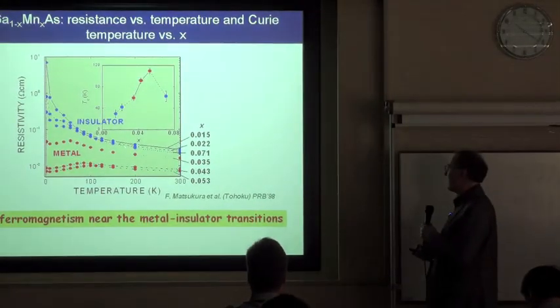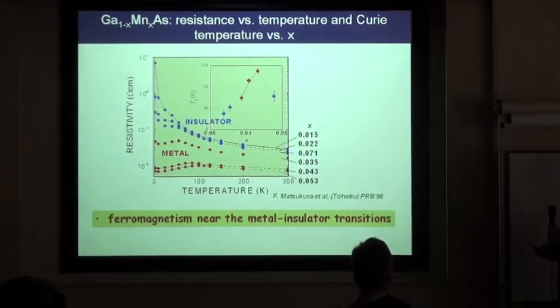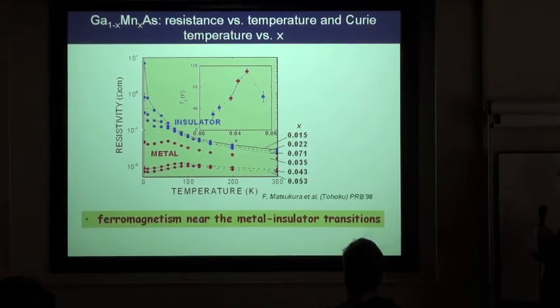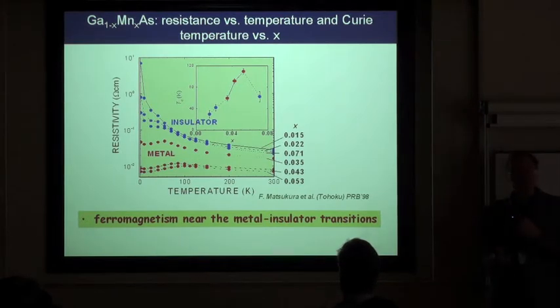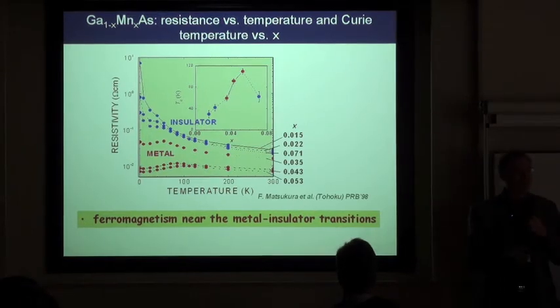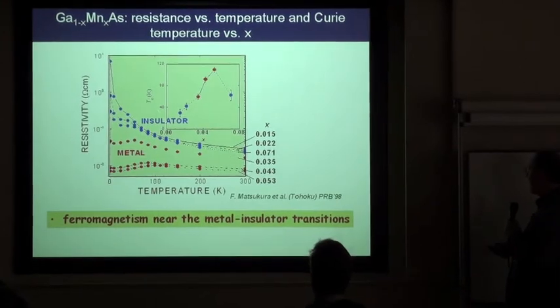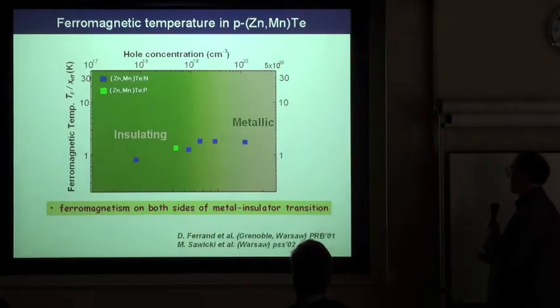the question is actually about these semiconductors, because even from the fields where we knew very well that we have localization. Here is resistance plotted as a function of temperature. It is clearly seen that in some samples this resistance goes to infinity, meaning that the samples are on the insulating side of the transition, whereas in other samples, extrapolating, the resistance has a finite value. So somehow the physics of these materials is the physics of the boundary of the insulator transition.